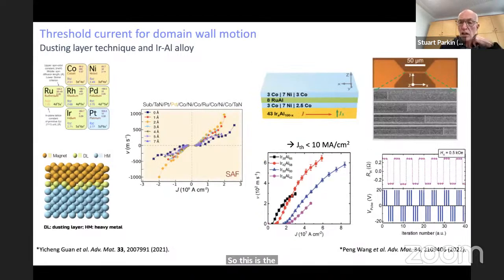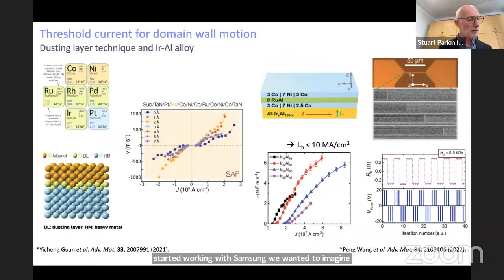I want to move then to electrical detection, but just to remind you, we also can imagine new materials that can allow for reductions in this threshold current density. Originally, when we started working with Samsung, we wanted to imagine Racetrack as a replacement for flash memory. And it turns out then you don't need the domain walls to move very fast, but you need low threshold current densities. And we were able to reduce the current density by almost a factor of 10 by changing the underlayer materials to a new set of materials.